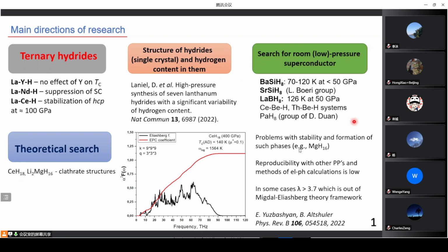For example, for this room temperature superconductor cerium H18, I took different pseudopotentials. I used the Perdew-Zunger exchange correlation functional, and I used tetrahedron integration to calculate the electron-phonon interaction coefficients for this compound at 400 GPa. And my result for different K and Q meshes is about 140 kelvins only. So it's a very big difference. I couldn't repeat these calculations of the group of Yanming Ma. And it's one of the drawbacks the theoretical approach suffers from.